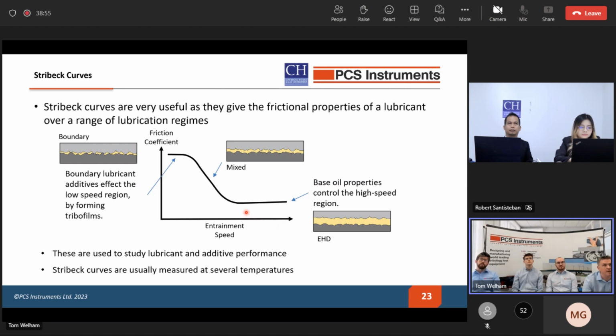As we move down through the speed range, we come into the mixed regime, where we're starting to have some interaction between asperities in the contact. And right down at very low speeds, we're getting towards the boundary regime, where there's significant asperity contact, and the load is being supported a lot by actual metal to metal contact. And when we can test down in this region, we can look at how tribofilms form to protect the surfaces in these regimes.